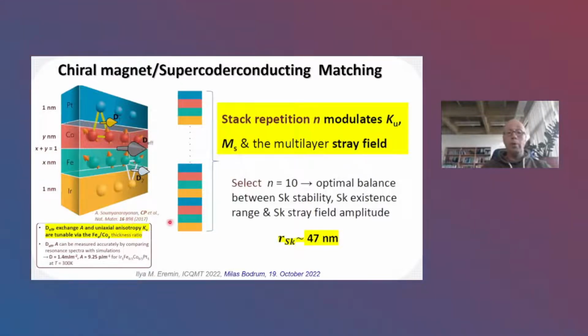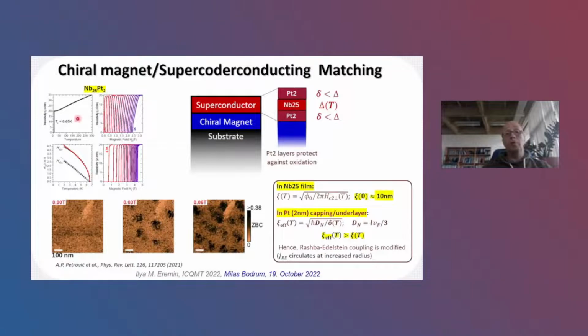Both were combined in the group of Christos Panagopoulos in Singapore, where they made some engineering in order to find an ideal match of elements, containing iron, cobalt, platinum, and iridium, in order to tune the strength of the Dzyaloshinskii-Moriya interaction and optimize the size of the skyrmions. This is what they did here for these heterostructures, with skyrmions of 47 nanometers. At the same time, they also used the superconductor niobium, with some coverage of platinum, in order to effectively modify the superconducting coherence length, and that's of course done in order to modify the size of the vortices. This is also what they have shown they were able to do.